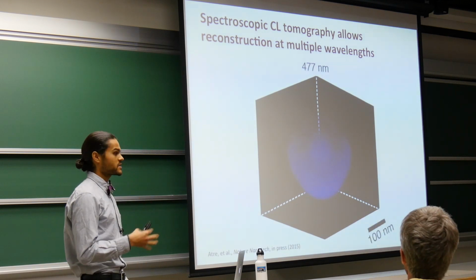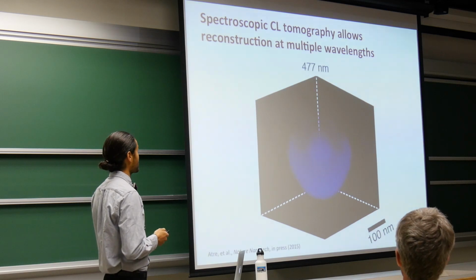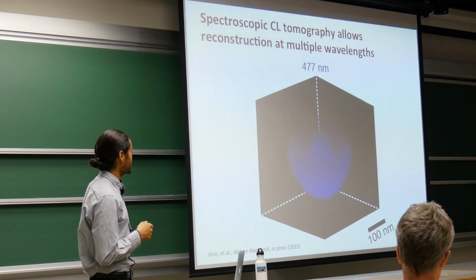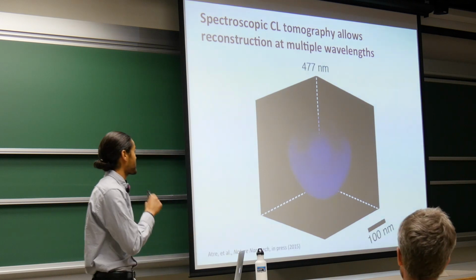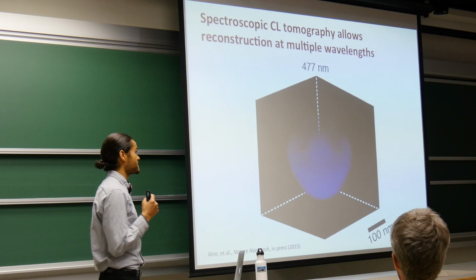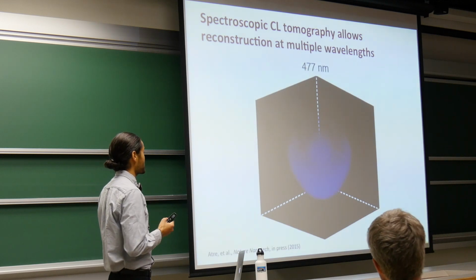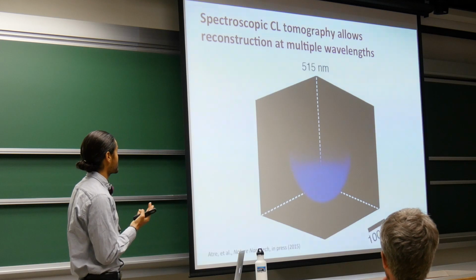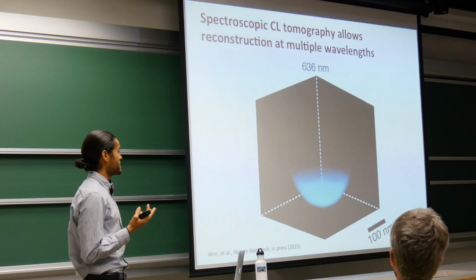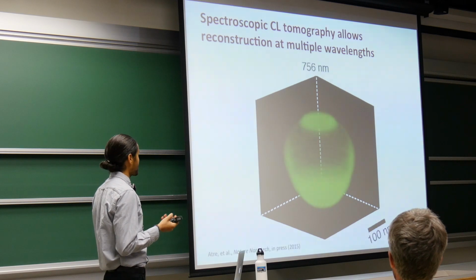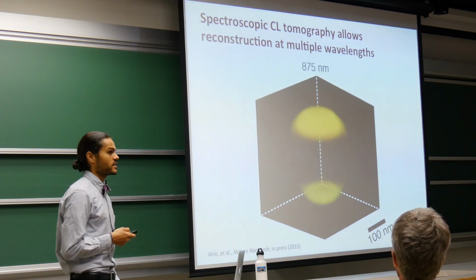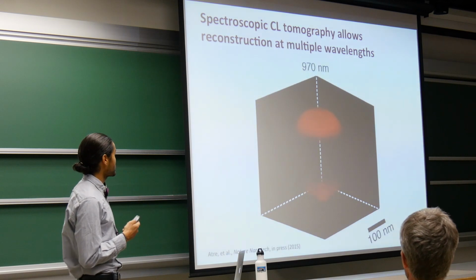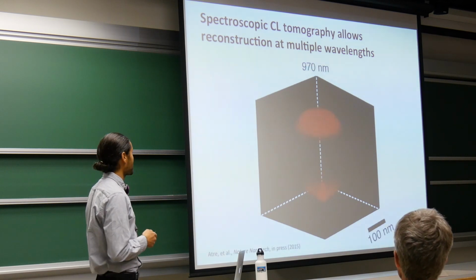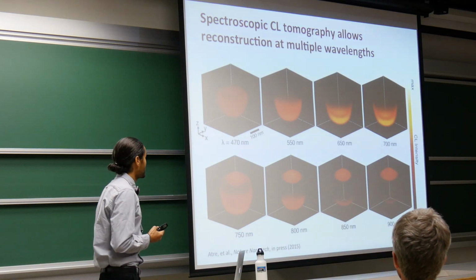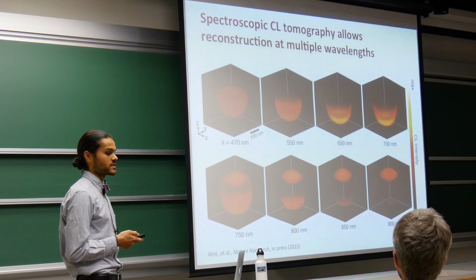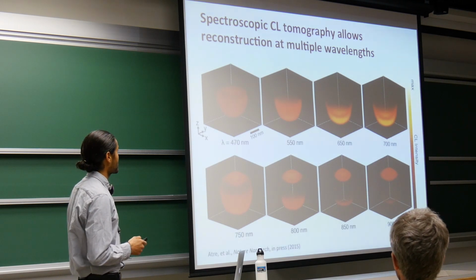So to pull this all together, we can plot out three-dimensional tomograms as we span the different wavelengths probed in this technique. Starting out here at a wavelength of around 477 nanometers, you can barely see it, but it turns out that there's actually some small signal coming from the polystyrene bead in the center of the tomogram, which is a pretty interesting finding. But at wavelengths around 500 to 700 nanometers, we see that the signal is primarily coming from the metallic shell, as I've mentioned a number of times, but then that changes, and as the wavelength gets closer to the near infrared, we start to excite that plasmonic mode at the tips. Looked at in a more static series of pictures, we can really see the evolution of this cathodoluminescent signal as a function of wavelength.